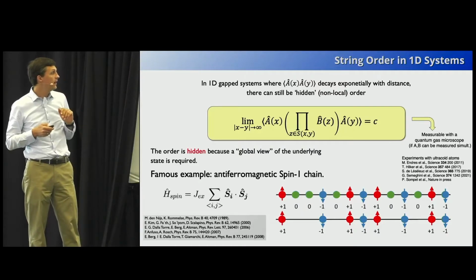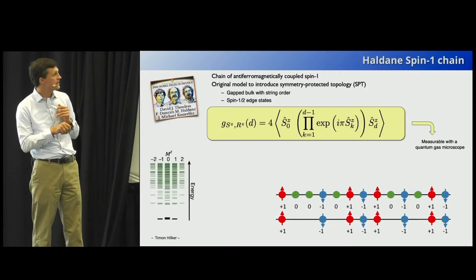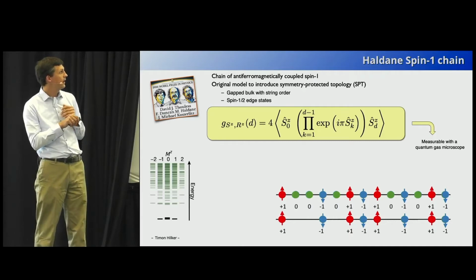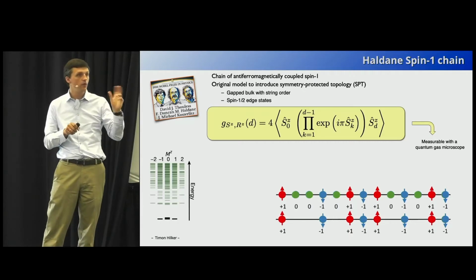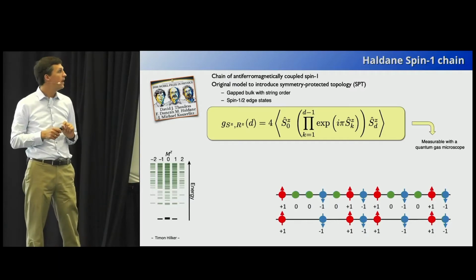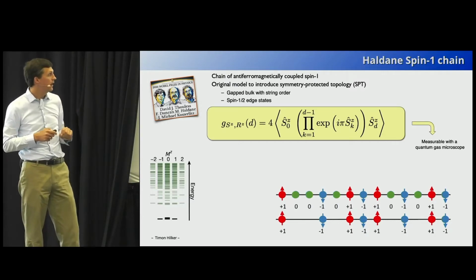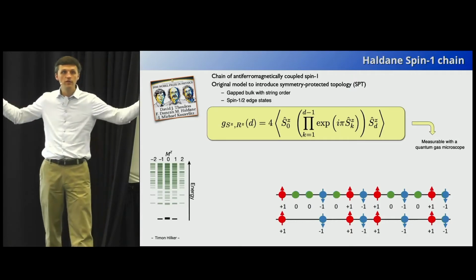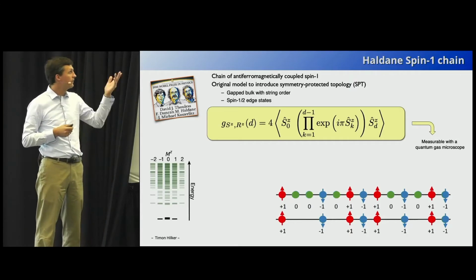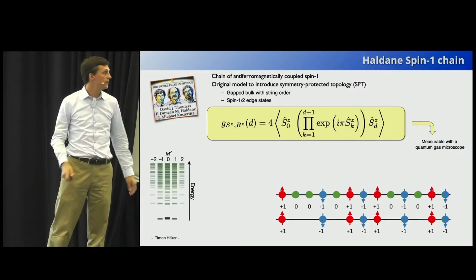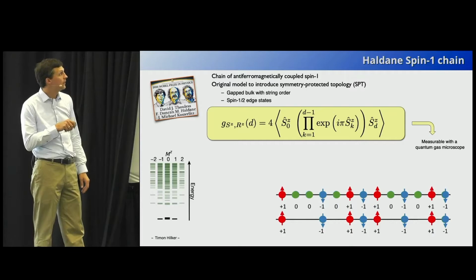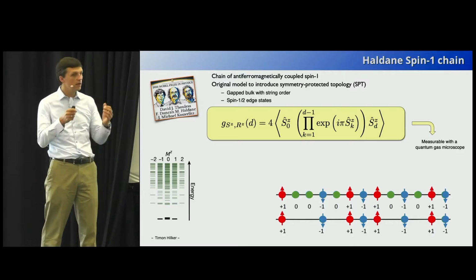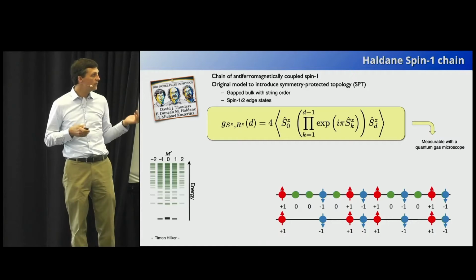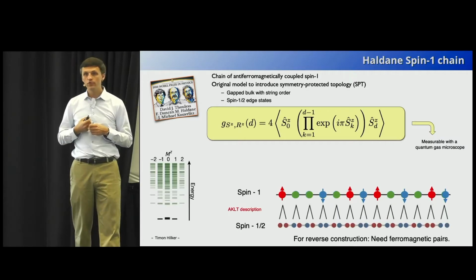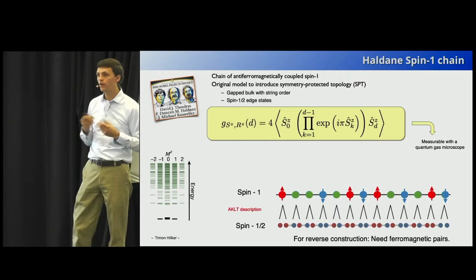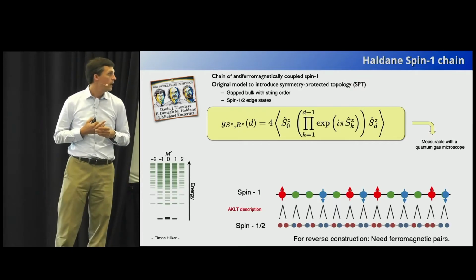And such a string correlator is now able to extract this. So if one just measures the spin Z and introduces this string, which basically counts the number of zeros in between and adjusts the sign accordingly, one does get a finite value, even in an infinite system, for such a correlator, so it forms an order parameter for this system. And of course, spin Z we can measure, so we've been keen to try this for a long time, but the difficulty is that one needs to be able to realize a spin 1 chain with antiferromagnetic coupling, and we only have spin 1/2 particles in our system.